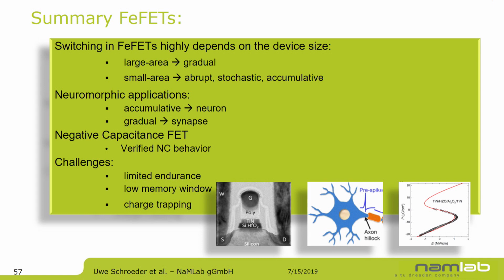And as I showed, so far we have 10^10, 10^11 cycles and the imprint, and so we have to improve a little bit on the defects within the hafnium oxide to further improve the field cycling behavior. But overall, if you look at the PZT case, it took also like 10 years to get something in production, and we just started like 10 years ago with everything so far.